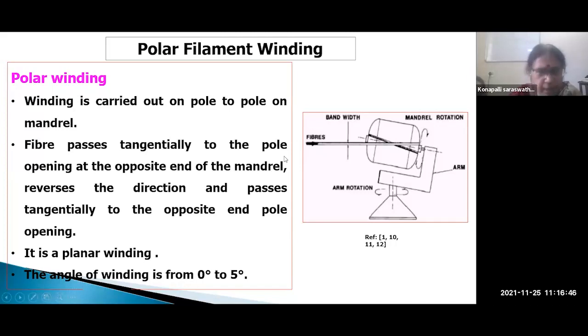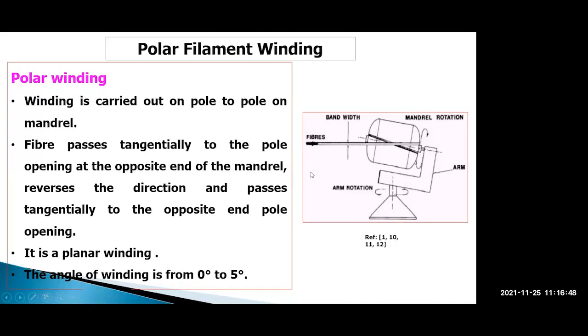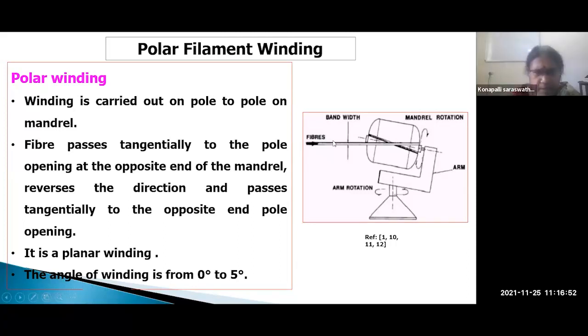So polar winding is carried out pole to pole on the mandrel. Fiber passes tangentially to the pole opening at the opposite end of the mandrel. From here it starts and gets deposited at the opposite end of the mandrel, then reverses, and again it is in the direction and passes tangentially to the opposite end pole. Then it will be indexed. So that is how pole to pole winding is done. It is a planar winding.